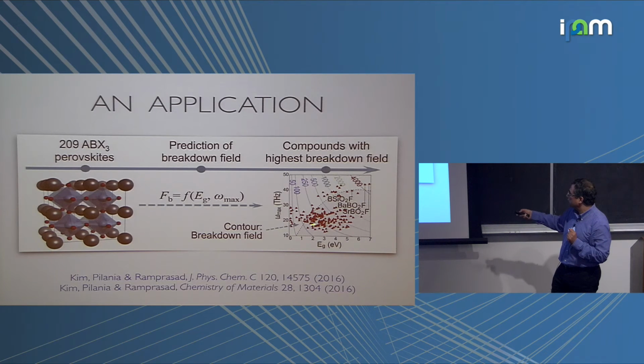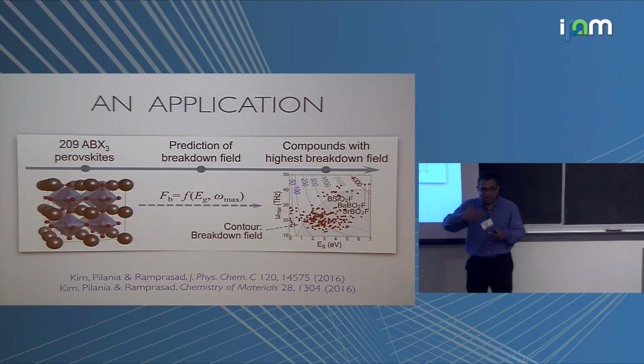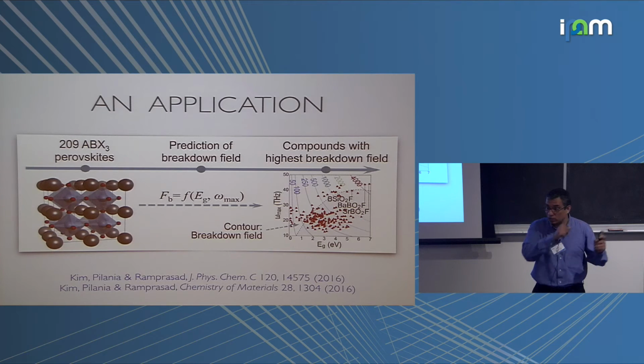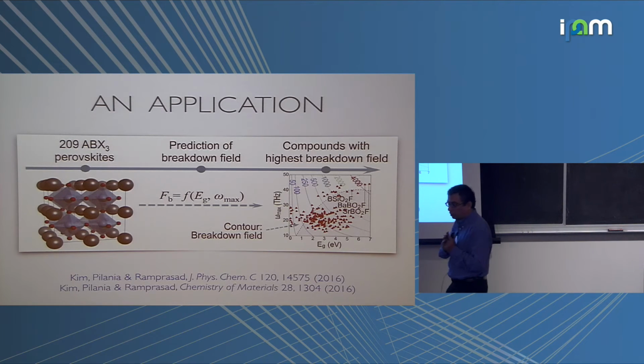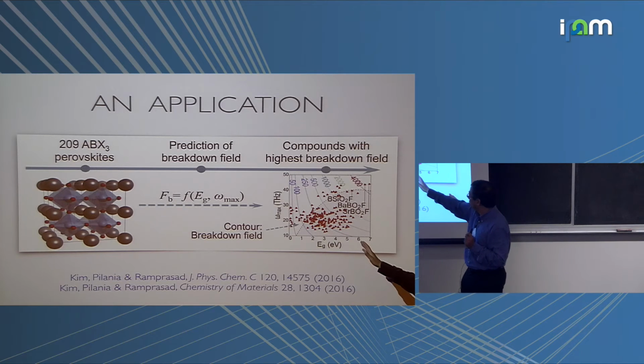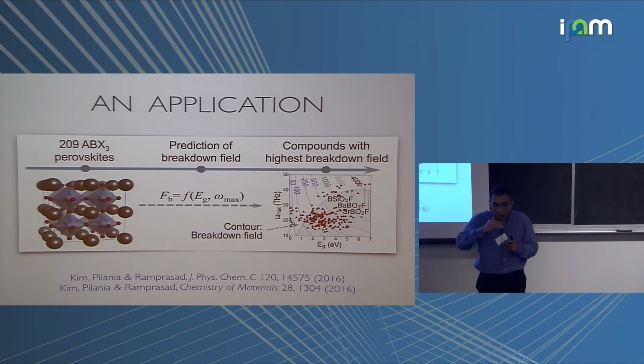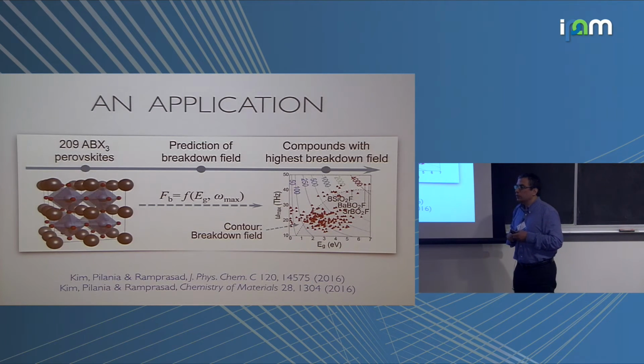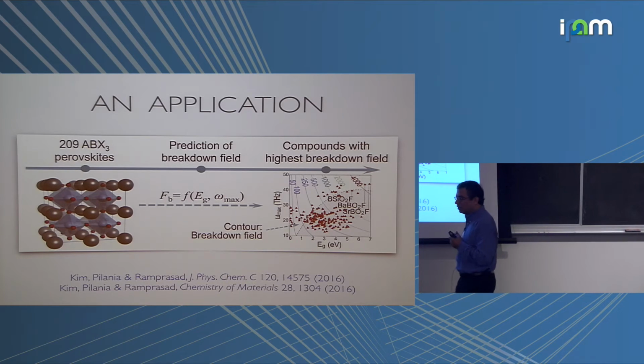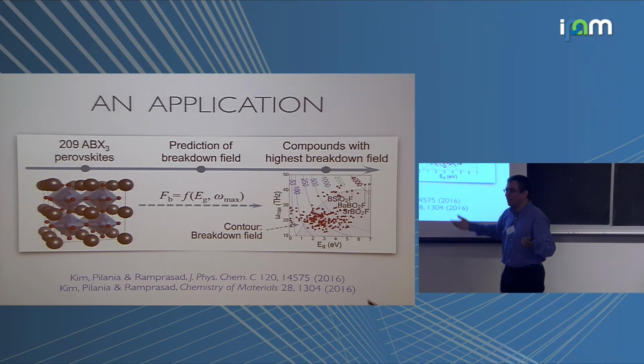Those are the red symbols. This dashed line that you see, the shaded region beneath the dashed line, that's the region that we actually believe our model to represent properly, because our data set of 82 binary octets have band gap and phonon cutoff in that shaded region. So if we are going outside of that, we are really going somewhat out of domain. Matthias, have you done a systematic investigation of the ability of these formulas to generalize beyond their original domain where they were trained? So we know that, yes, we are interpolation models. Yeah. All of these. We are working on that right now because we have a bigger data set, right?